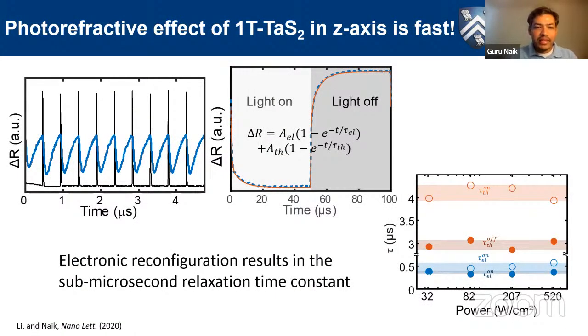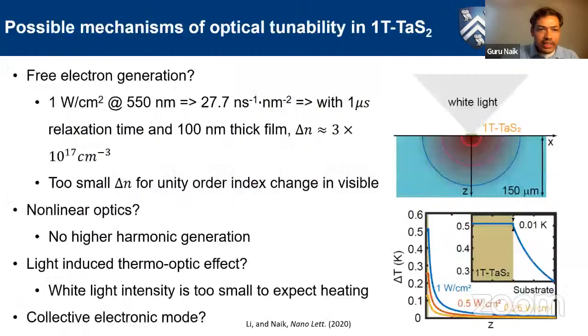So we did some time domain measurements as well. First of all, what we found out was the time constants are on the order of microseconds, actually sub-microsecond, just hundreds of nanoseconds. It's not very fast, but it's still in the sub-microsecond regime. And another thing that we saw was that the time constants do not change. These time domain measurements were all done with laser. This is not white light. So we also had some heating of the sample. So we had two time constants, the thermal time constant and another, which we think is an electronic time constant. And we saw that they don't show any power dependence, which is good. So we can think of a simple thermal model for our material. So that's what we found out.